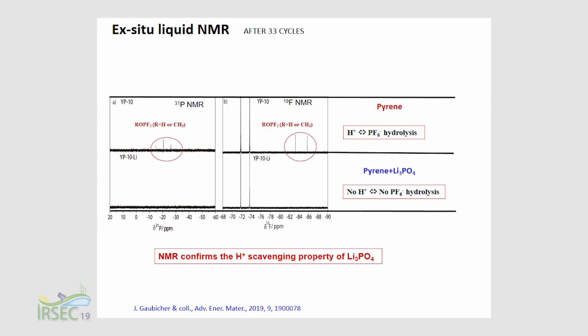I've done also liquid NMR with the only pyrene electrode. After a few cycles, we find these signals for phosphorus and fluorine NMR, and these signals correspond to the hydrolysis product of PF6, which has reacted with HF. And in fact, when we add the Li3PO4 in the electrode composition, after cycling we do not have these signals. This means we do not have protons in the cell. So this confirms the proton scavenging properties of Li3PO4.